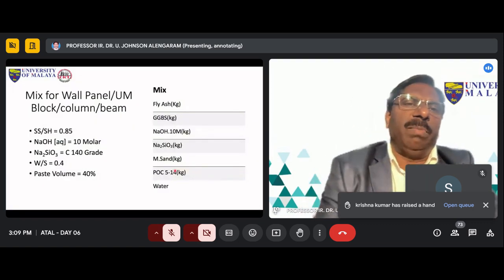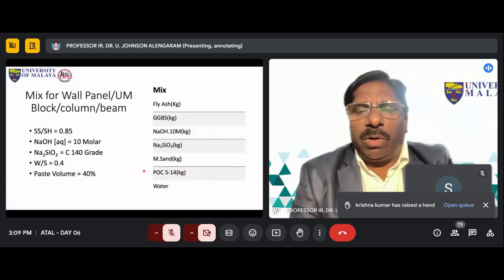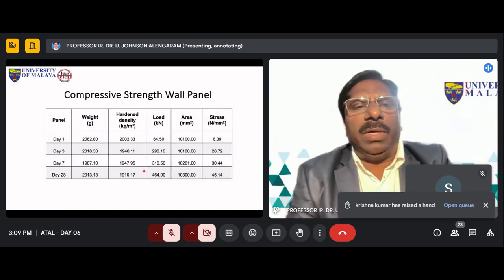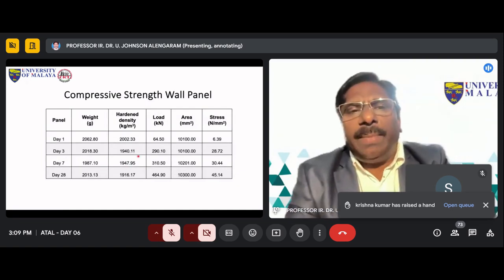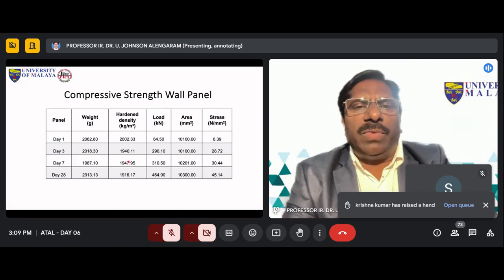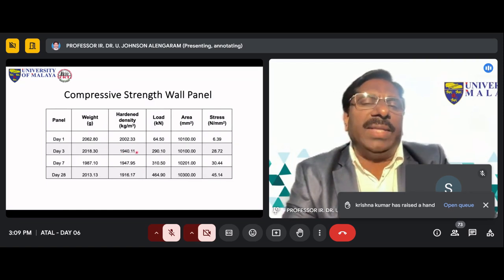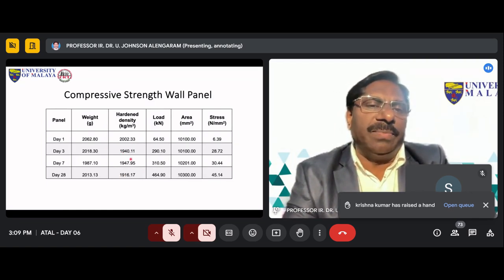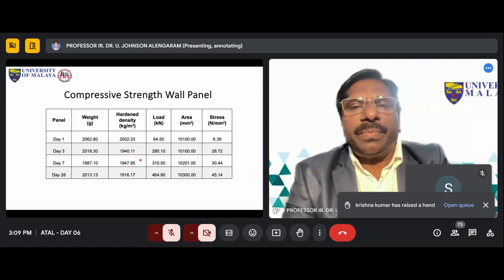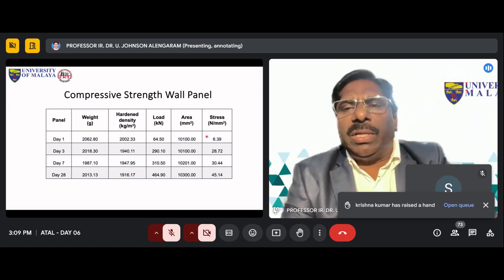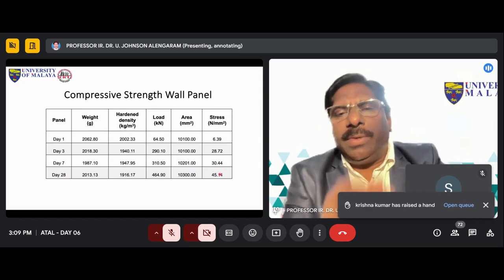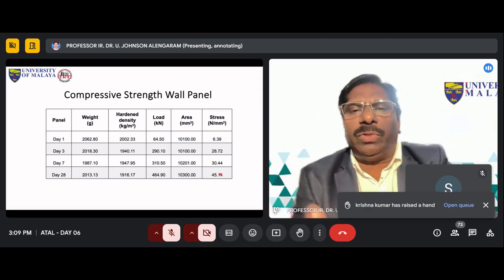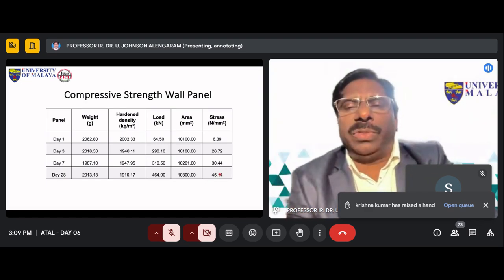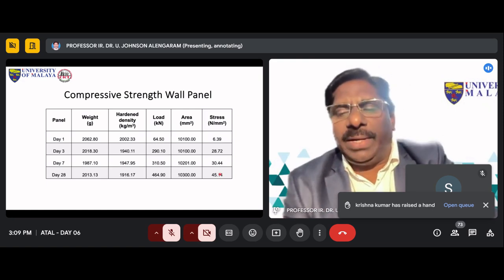This building was built using geopolymer concrete, and these are some of the interesting data. What we did was most of our densities were less than 2,000, which means it's lightweight concrete. And the strength of this material, even at 28 days, we managed to get 45 megapascal. This is purely cement free. We did not use any cement at all. We don't show all the materials here, but we used cement-free materials, 100% eliminated cement.